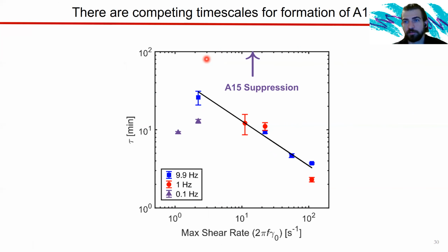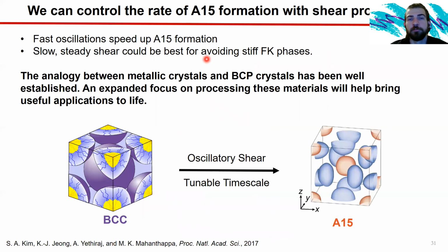So what this tells me is that there are competing timescales for the formation of Frank-Kasper A15 from this metastable BCC state. Now, this is a balancing act, right, between what phases are stabilized during shear and what phases are not. So when you start shearing the sample, you're going to have an increase in intermicellar collisions, right? You're sliding these layers between each other. Now, I think that's increasing the rate of chain exchange where the molecules can then jump between each other. And if the conditions are right, this will help us get to our prerequisite aggregation numbers for A15 formation a lot faster.